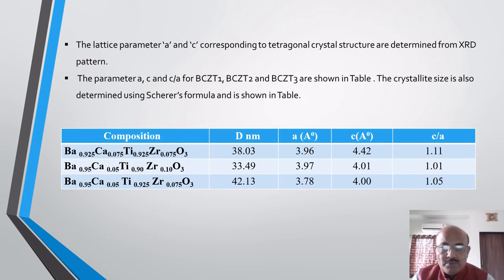Now, if we observe the table, we find that the crystalline size is very small, being of the order of 38.03 nanometer, 33.49 nanometer, and 42.13 nanometer. According to the calculation of a and c, the c/a was about 1.11, 1.01, 1.05. This observation is the same as reported.